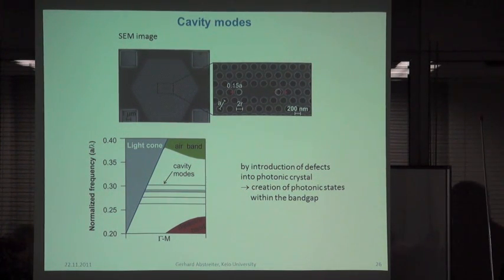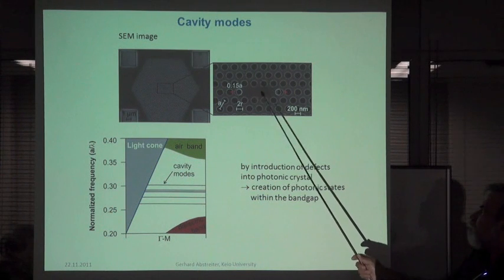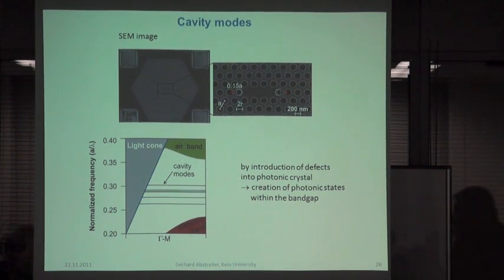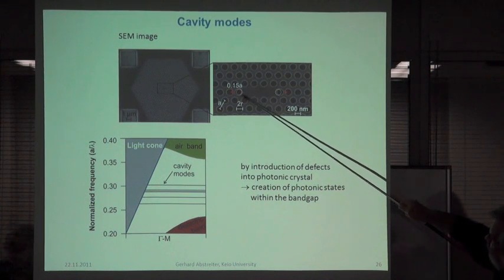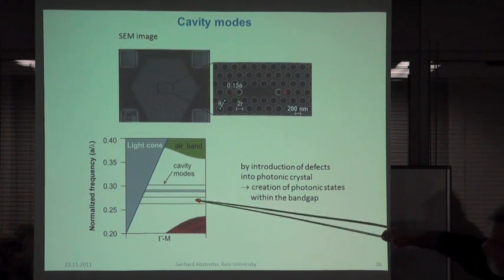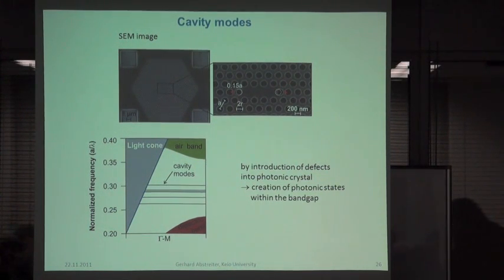It's also, I have a band structure for photons, and I have a defect here, and this gives me just states in the band gap. And in this kind of cavity, which is often called an L3 cavity because 3 holes are missing here, we get these 6 cavity modes in the system.